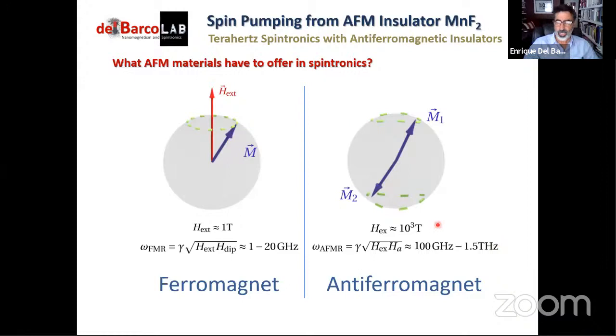And this is what happens with antiferromagnetic resonance, but this is known as exchange amplification. So basically the anisotropy, the internal energies of the antiferromagnet, are amplified by this strong exchange coupling that we have. This actually happens with any magnetic perturbation that you add to the system. So for example, if we're talking about injecting a spin current into an antiferromagnet and expecting the spin transfer torque to add to the sublattice magnetizations, that is more magnetic perturbation. That leads to gigahertz frequency dynamics in ferromagnets, but will now be amplified by the exchange interaction and lead to terahertz dynamics in some cases.